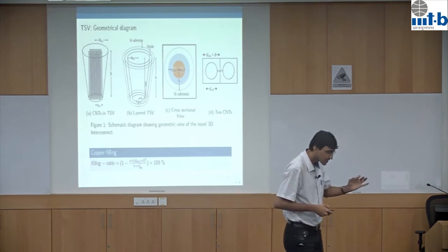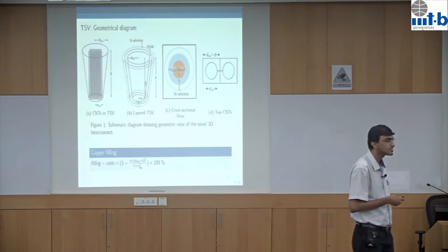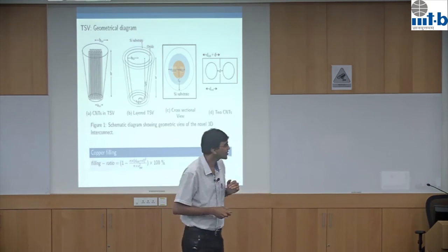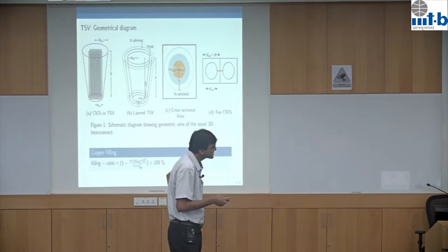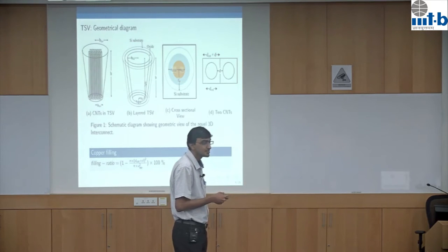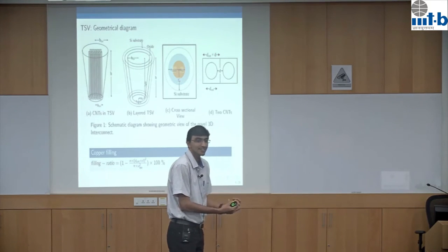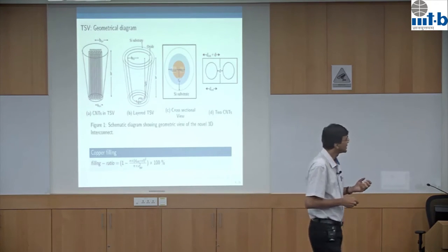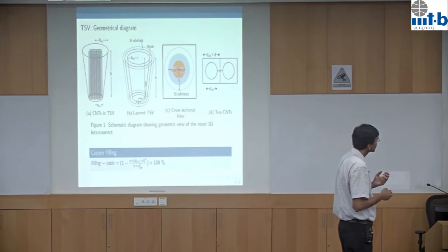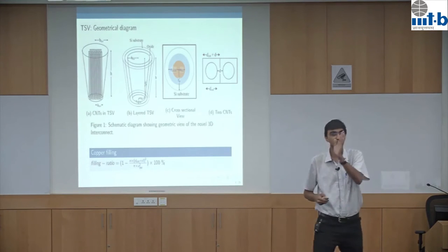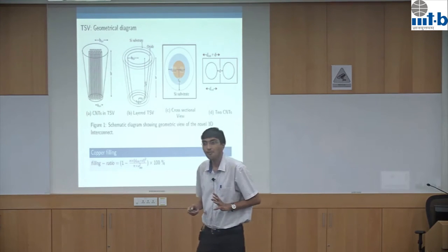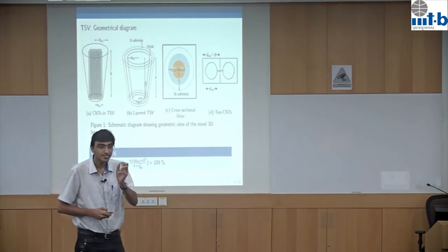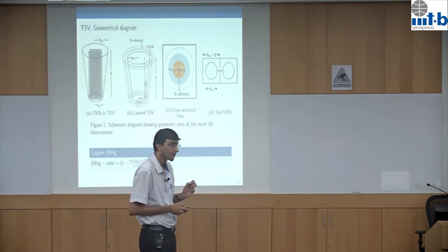And another point about carbon nanotubes is that they actually grow from bottom to top. So it needs some kind of a base region where it starts, there is a catalytic moment, and then it starts to grow. I cannot actually grow this carbon nanotube somewhere on the tapered profile, somewhere on the sidewalls. And then there is a distance between each of these carbon nanotubes.